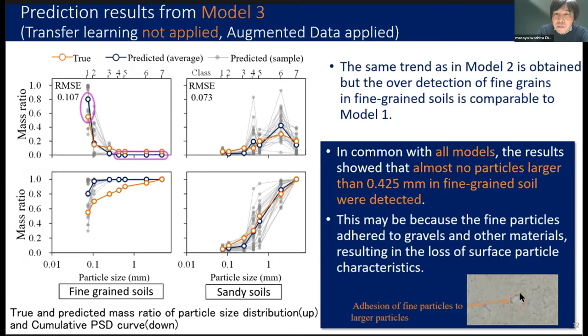Fine soils smaller than 0.075 millimeter are powdery and adhere to the surface of the larger particles. This is thought to be caused by the loss of characteristics unique to large particles, making prediction difficult. This idea is supported by the fact that such results do not occur in sandy soils with a low fine particle content.